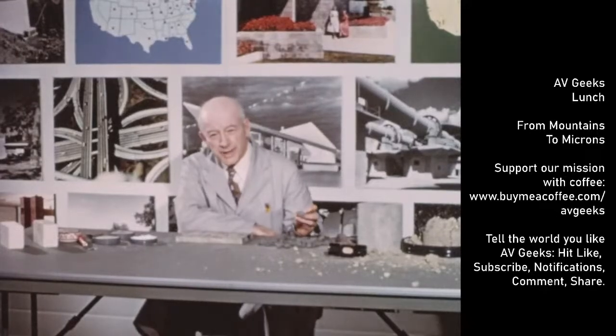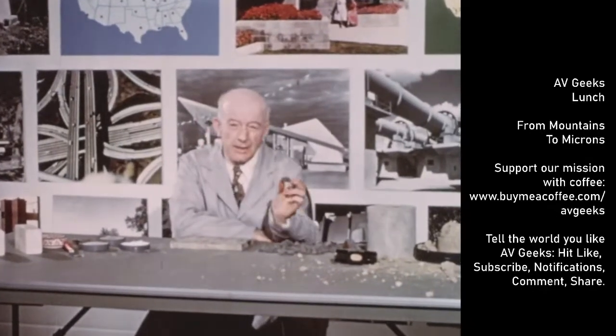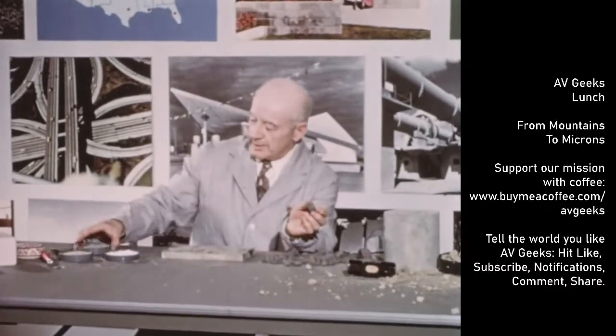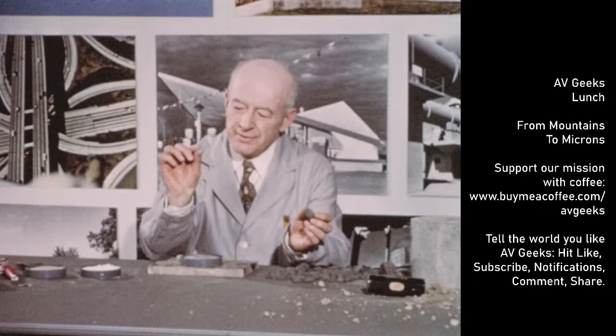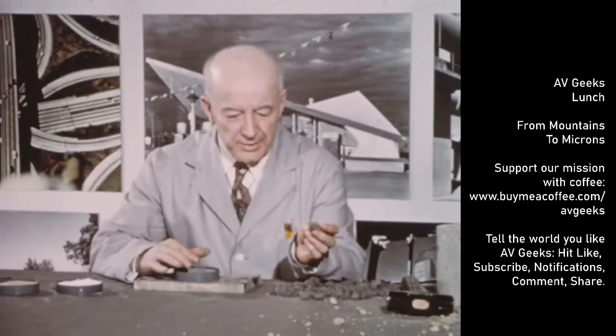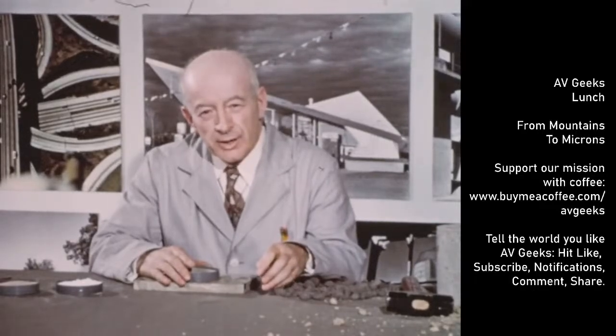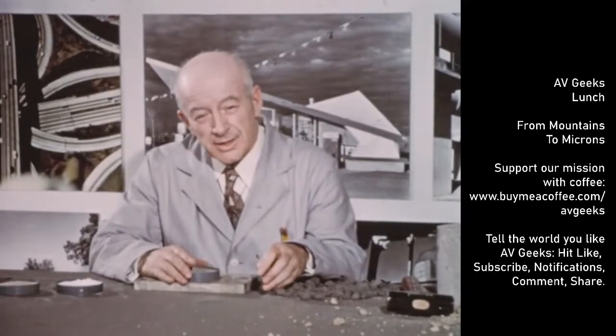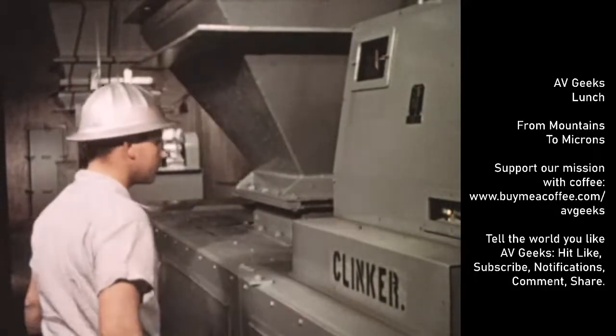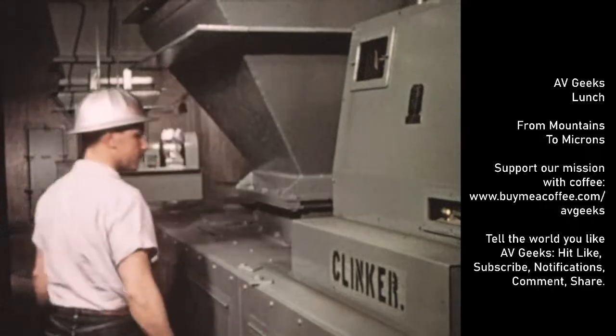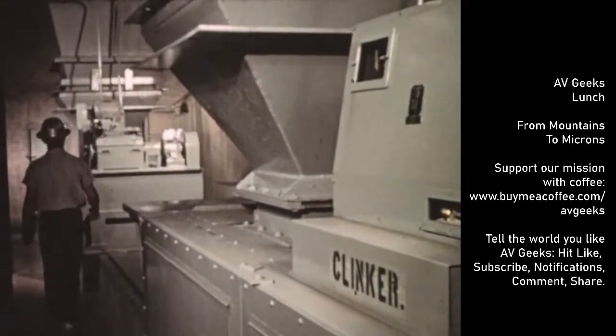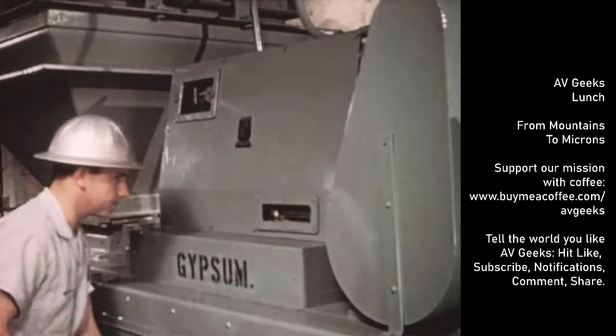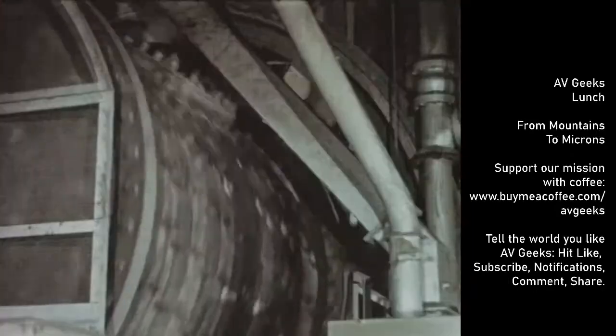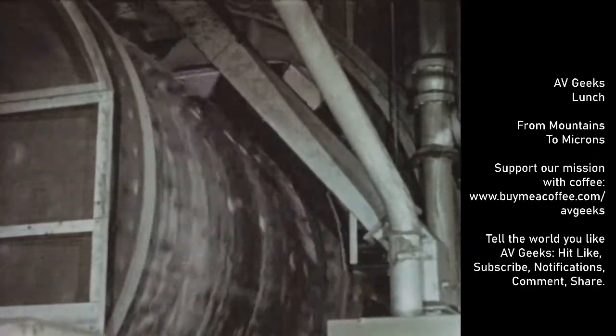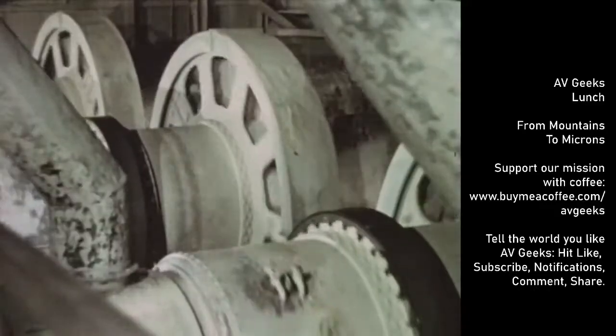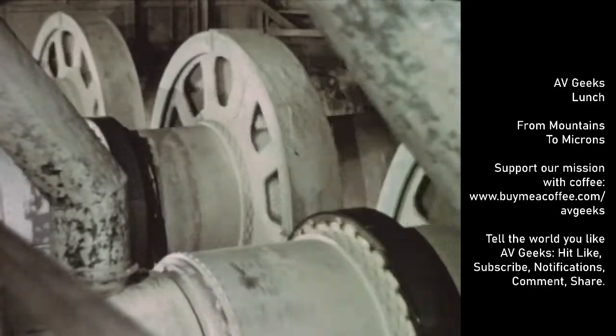The final stage in the manufacture of Portland cement is the fine grinding that reduces the clinker to a powder made up of particles the size of microns. This process employs some of the same massive moving equipment that has been used in previous processing steps. Before final grinding, a small quantity of gypsum is added to the clinker. This aids in regulating the setting time when the cement is used in making concrete. Now the clinker is charged into rotating ball and tube mills, where thousands of steel balls grind the material to the superfine powder that is Portland cement.